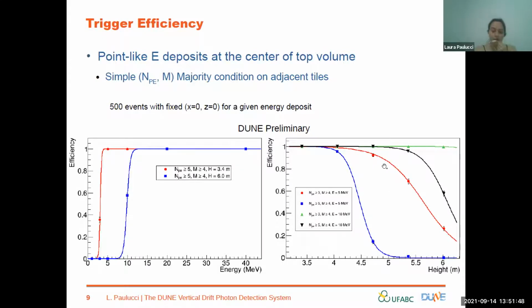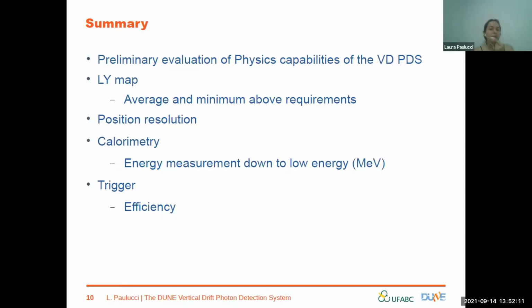So of course, the larger the energy deposit, the better the efficiency for triggering. And of course, as you loosen this majority condition, you also have more efficiency, but you can also have less purity. That is still one thing that we need to do. So very preliminary, we have identified that the vertical drift PDS has the capabilities of allowing for a very low energy threshold for detection. We have a preliminary light yield map position, an energy resolution, and also trigger efficiency.